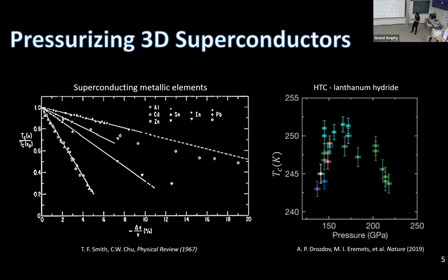Under pressure, at least at the beginning, pressure enhances the superconductivity in those materials. The critical temperature increases, as you can see, up to 150 GPa. The Tc increases to around 250 Kelvin, which is pretty high, much more than lead, indium, and the other elements. And in those high temperature superconductors, the understanding of exactly what pressure is doing to the sample is much more complicated. It differs from one material to another.